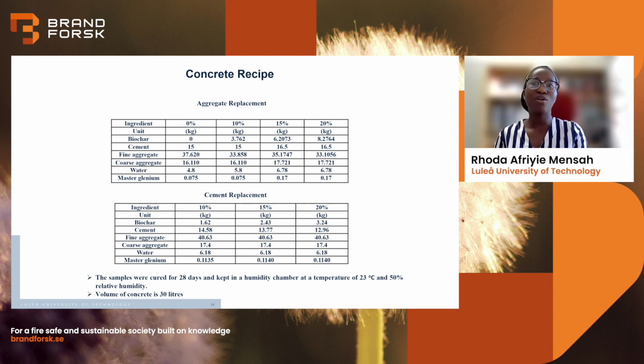So in all, we prepared 7 batches, including the control sample, and about 30 liters of each batch was prepared. After the concrete preparation, we molded them in cubic and cylindrical molds, and they were cured for 28 days, after which we placed them in a humidity chamber that was set to 23 degrees Celsius and 50% relative humidity.